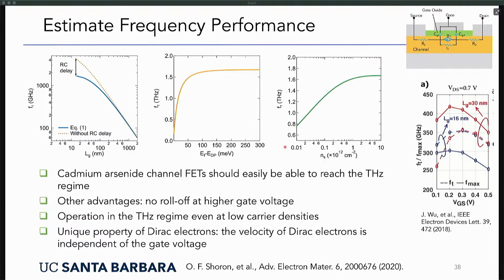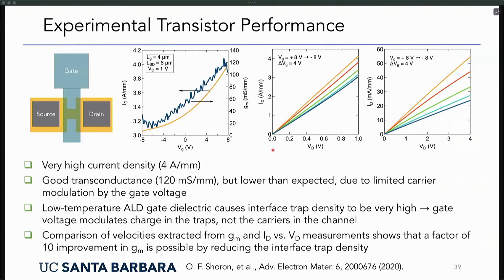Okay, so these are calculated properties. This is not measured properties, but they're based on the experimentally measured parameters of these cadmium arsenide channels. And so of course, one should check once it gets into the experiment. So here's the first results from making transistors out of cadmium arsenide. As expected, we get very high current densities, that I already showed you here, and that could be pushed higher, going to higher voltages.